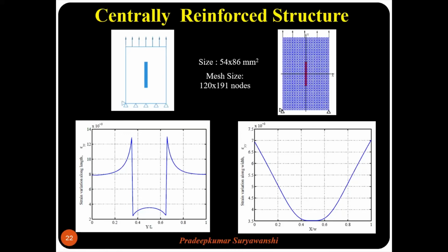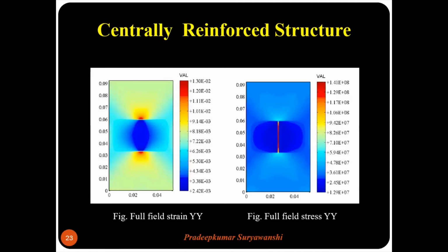Then as we move from left to right, this is the variation of epsilon yy along the horizontal, along the x direction as shown here. On the extreme left there is a large strain, and in the inclusion there is negligible strain, and it increases as we move in the matrix material. These results are in good agreement with the results presented in the literature. This is a very important slide as far as the centrally reinforced structure is concerned. Now in this slide I am showing you full field strain and full field stress.